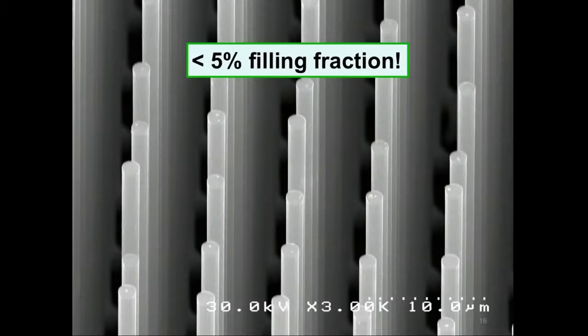Well, actually, we get fortunate by design, because the spacing is on the dimensions of the wavelength of light. So ray tracing optics doesn't work here, nor does Bruggeman effective dielectric medium theory. In fact, because these are high index of refraction rods, any photons that are scattered are multiply internally reflected and are optically trapped in those rods as optical concentrators. And so actually at normal incidence, even in this array, we get 25% light absorption, and you saw that that material looked black. The reason it looks black is that off normal incidence, you have a lot of internal scattering and long path lengths, and you get essentially 100% light absorption.